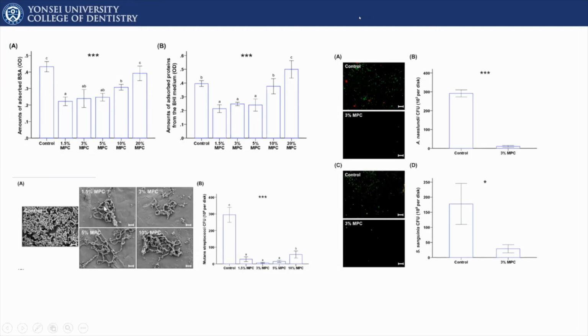Even at a low dose of 1.5% to 5%, it reduces the attachment of Streptococcus mutans, as well as two other early colonizers of biofilm, which has been significantly reduced by just 3% of MPC added to fluoride varnish.